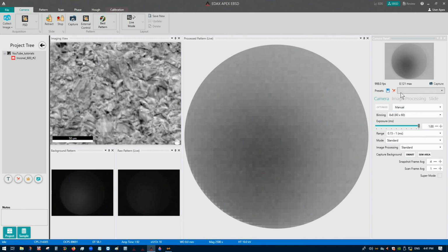The problem, though, is this is a little too low for the intensity fraction, okay? So we need to increase our exposure time, but we can't go any higher here, right? We're topped out at 1 millisecond or 1,000 frames a second. So we have to go up to the next slider here, and now we can increase our exposure time. You can see our frame rate is going down, but our intensity fraction is going up.